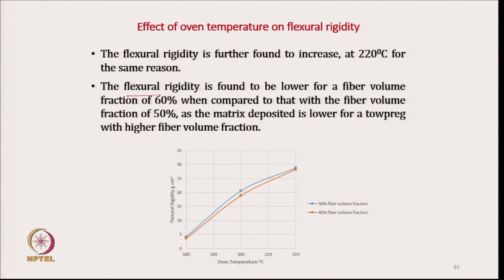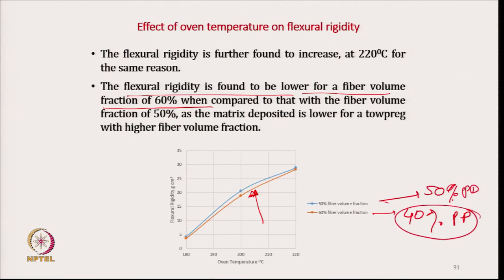The flexural rigidity is found to be lower in case of 60% volume fraction. It is lower because the polypropylene, which is responsible for enhancing the flexural rigidity, is lower in content. So, 60% fiber volume means 40% is PP, here 50% PP. So, due to lower quantity of polypropylene, the flexural rigidity of 60% volume fraction is lower than the 50% volume fraction.